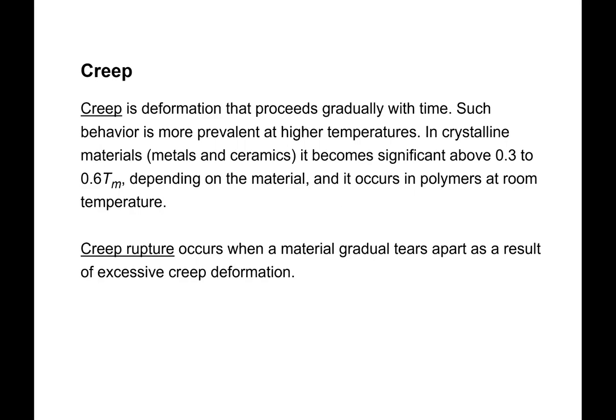And by high temperatures we're talking about greater than typically about half the melting point. So you'll see a range of anywhere from 0.3 to 0.6 times the melting point. But once you start getting to a significant fraction, so 30% of the melting point, then you should start being concerned about creep and double checking that in terms of your design.